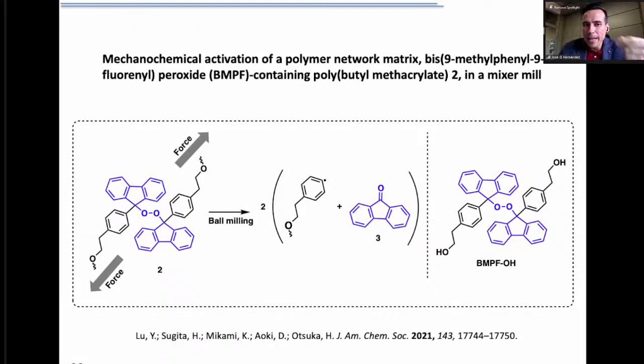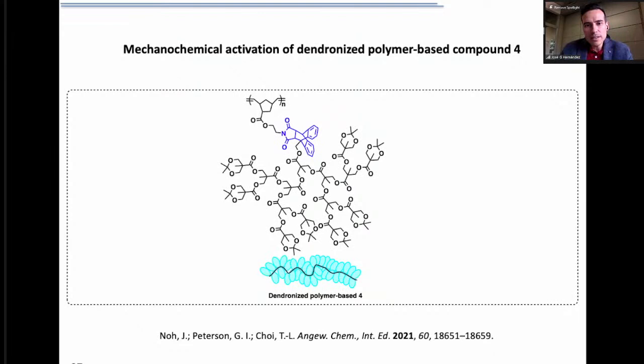Are there comparative studies? Well, last year there was another study reported in which the authors synthesized bottlebrush polymers and also dendronized polymers, such as the one I'm showing here. That polymer also contained a mechanophore right here. And they tried to see what was the consequence of sonicating this polymer, or the consequence of putting that polymer within a container, a mill, for a while. They observed that if you sonicate this polymer, what you observe most of the time, and practically exclusively, was the backbone cleavage. You don't really see activation of the arms that contain the mechanophore.